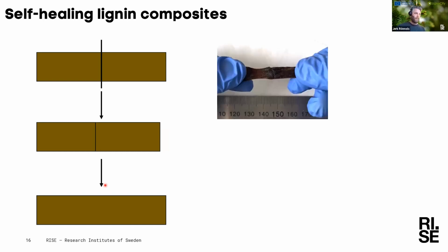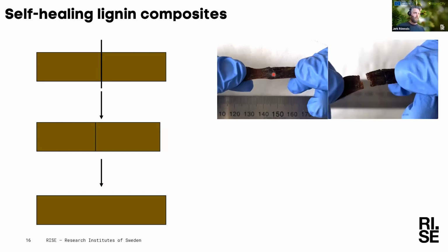So that is what we're seeing, for example, here. You can still see the cut. So this piece was cut here and then pushed back together. And then Xinyi is pulling these apart again. And what happened in this one actually was that when pulling the second time, it broke at a weaker point on the side here and not where it was initially cut. So when it heals, it is actually very strong, and sometimes even stronger than other parts of the material.